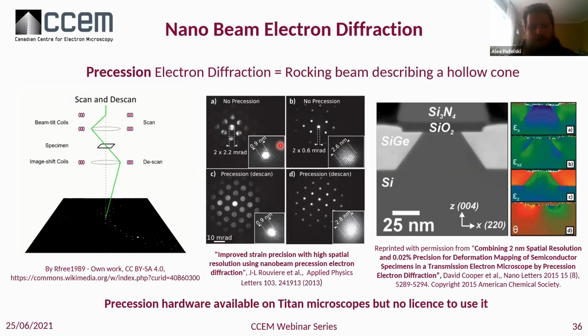You have this nanoprobe mode here, and I think this was done on silicon germanium, and you can see some features inside here. So 1 nanometer resolution and 2.2 milliradian semi-convergence angle, and this is with precession off, and this is with precession on, and you can see how the intensity distribution changes inside the disk. And probably here the strategy to do the processing will be different. In here you also have more spots that are illuminated, and the intensity is more uniform. Of course, on the processing side, the world is huge, so there are probably some great strategies for tackling that. But I have the feeling that using the precession method makes the processing easier here. And what is very interesting is that there is no loss of resolution in that aspect.